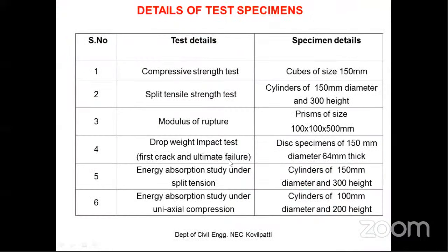So these are the details of the test specimens. These are the normal specimens. Compressive strength has been checked, split tensile strength, the modulus of rupture, drop weight impact test. Serial numbers 4, 5, 6 deal with the energy absorption mechanisms. Energy absorption under split tension has been studied with cylinders of 150 mm diameter, 300 mm height. And the drop weight impact test was conducted on a disc specimen 150 mm diameter, 64 mm thick. The specimen sizes are taken from the ACI 544R recommendations.